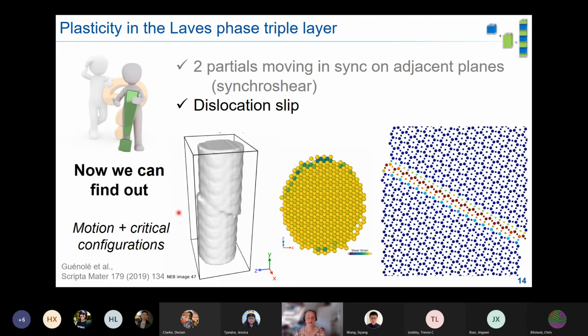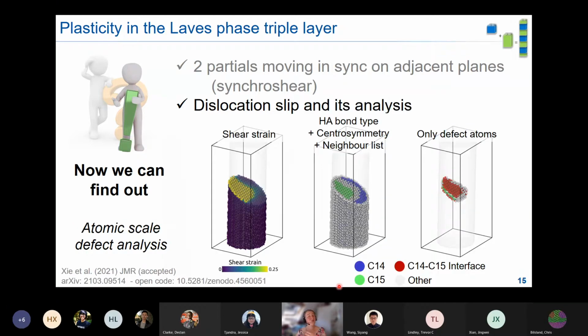So that means we can now find out how these dislocations might move. And I think what's most important to me is we can find the critical configurations where we can then go and be more flexible, do DFT, and actually compare different crystal structures. One of the difficulties we had in this was actually that if we want to look at dislocations in a volume that we've deformed in the computer, then the normal visualization strategies that we use in, for example, HCP or FCC crystals, they don't work. They're not geared for these kind of structures.